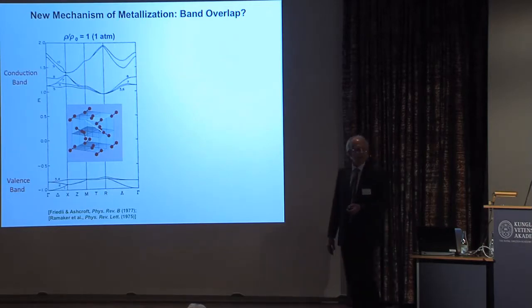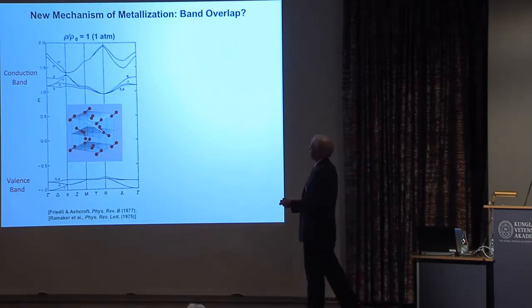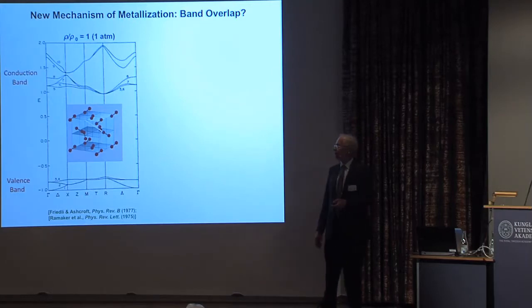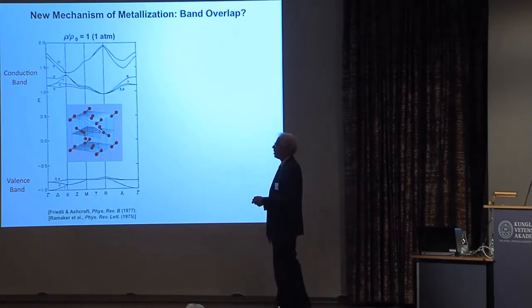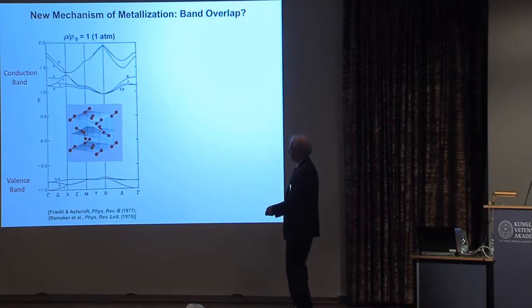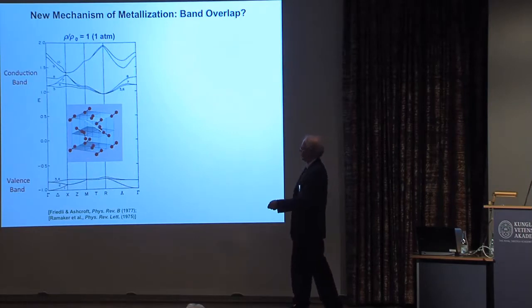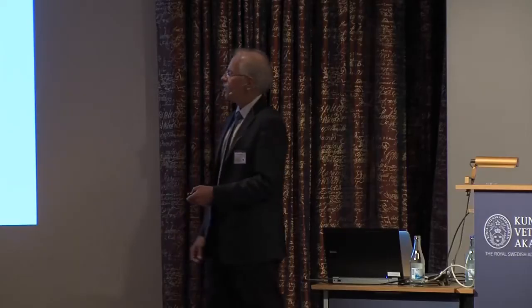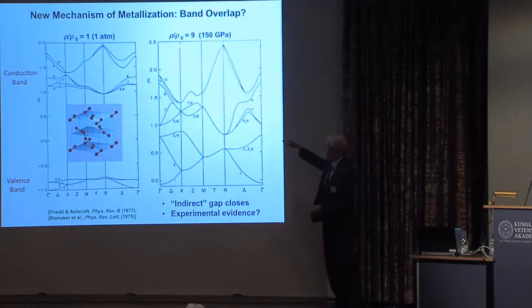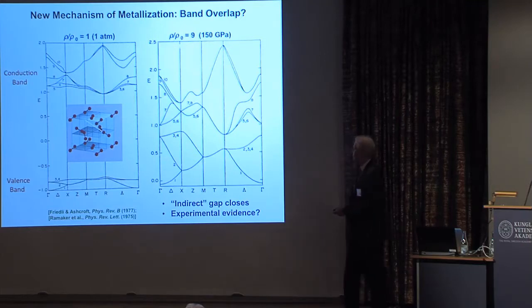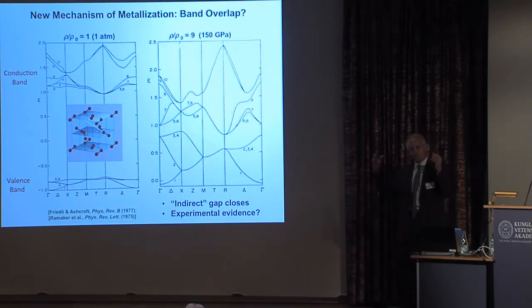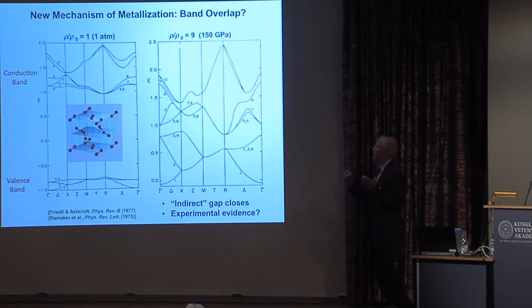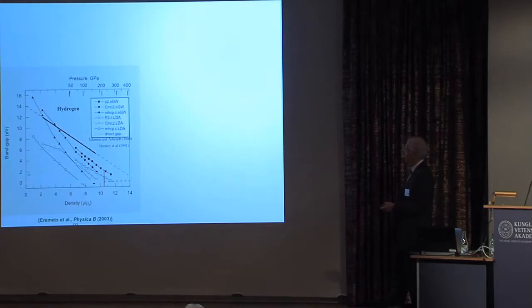Well, is it a metal? Well, it turns out that with increasing pressure, there's a different mode of metallization, and that is band overlap. And this was pointed out in a series of calculations done in the 1970s. What this means is there's a gap between the valence band and the conduction band for the molecules in the solid, and with increasing pressure, they can overlap. And this so-called indirect gap closes to form a metal. So it's a metal, but the molecules are still intact, so a band overlap metal, a second kind of metallization mechanism. Is there any experimental evidence for that?